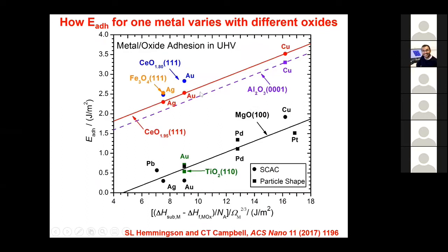So most of the points that we can make a line with are the only points where we have multiple points. And now we have nickel in it also, right where it should be for slightly reduced ceria. So adhesion energies are much, much stronger to ceria than to MgO. But the correlation, oxophilicity per unit area, is still there.